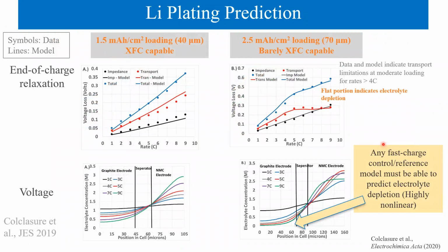To further investigate the nature of the difference in charging behavior between the low and moderate loading cell, the overpotential at the end of constant current charging was characterized by current interruption voltage relaxation. This analysis is focused on distinguishing between overpotential associated with almost instantaneous phenomena, impedance, and that has a characteristic time, transport.